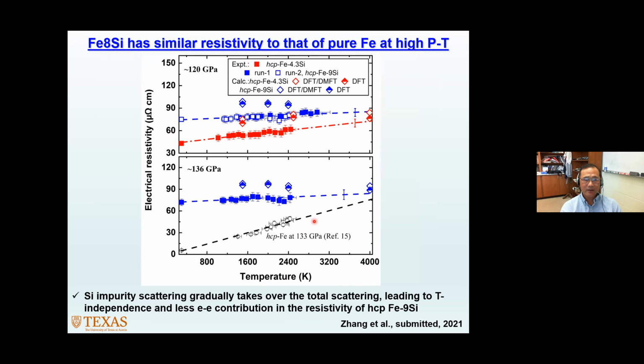So let's focus on this panel here. Again, the pure iron data for the electrical resistivity as a function of temperature. But for the iron with 8% silicon, and this is also in HCP crystal structure, there's almost no temperature effect. So instead of temperature-dependent resistivity, this is almost temperature-independent resistivity in iron with 8% silicon. So the theoretical calculations by Ron Cohen and colleagues indicate that the reason for this is really the silicon impurity effect that